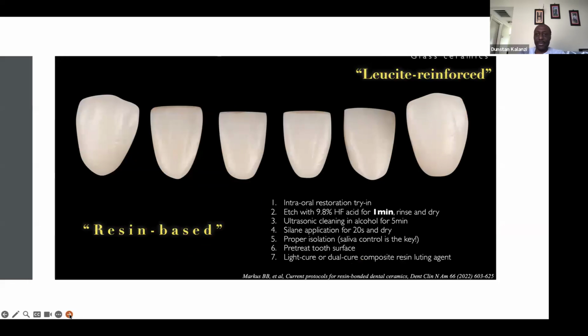The same would apply with the glass ceramics, and here I'm talking about leucite reinforced. You might use a hydrofluoric acid of a different strength, but you still wash it away, and then use silane application. Silane allows the resin to bond to the restoration. That's why you silane treat after etching with hydrofluoric acid. And then you can use your light cure or dual cure composite resin luting cement.